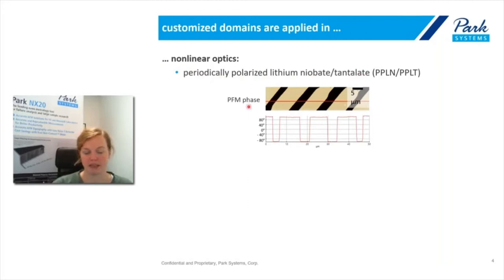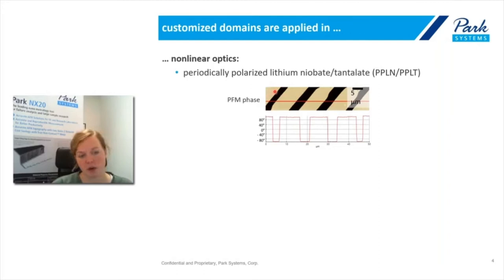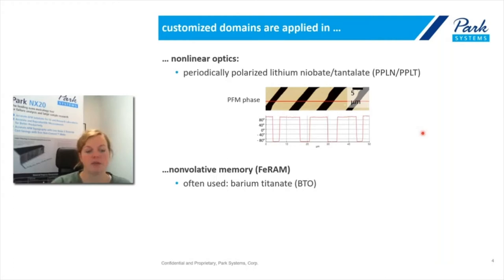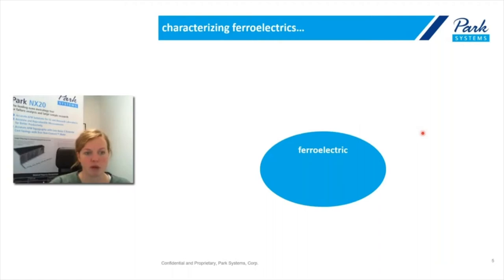The materials typically used in non-linear optics are lithium niobate or lithium tantalate. Here we have a PFM phase image of such a periodically polarized lithium niobate, or PPLN, and we can nicely see this periodic pattern in the PFM domain — bright contrast and dark contrast, meaning one domain is oriented in one direction and the other domain is oriented in the opposite direction. The writing of domains can also be used for memory devices, where ferroelectric material is used as the active layer and information is stored by switching domains as desired. A material often used here is barium titanate.